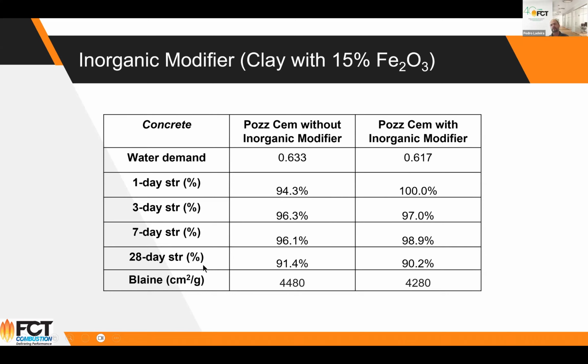What the message behind this is that we managed, by the utilization of an inorganic modifier, to obtain better results in early strengths, which is one of the alleged weaknesses of the whole utilization of calcined clay for cement. So we can overcome part of the loss in the reactivity of LC3 compared to the OPC cement.